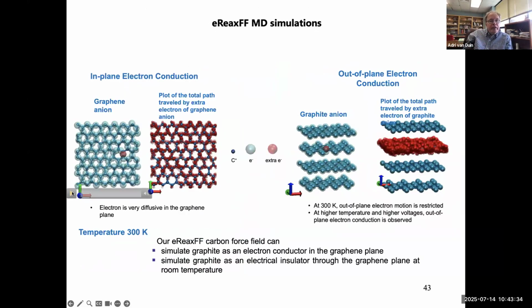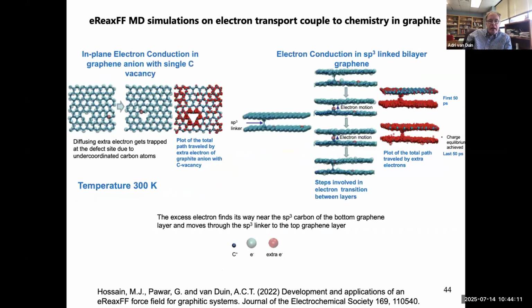And then we managed to actually simulate electron transfer. So we can actually do a concept of electron mobility. To guide your eyes, the extra electron here is colored in red. It's really the same electron as all the other electrons. We can see it can hop around in the 2D direction. And over time, it really looks like the DFT picture. So the extra electron pretty much has an equal capability to be everywhere in the lattice, which is clearly what you expect to see. But also it only moves in the 2D plane. It doesn't move in the 3D direction. In graphite, it doesn't hop between the layers. It just stays located in the 2D direction. So this was published in 2022, as you see here below.